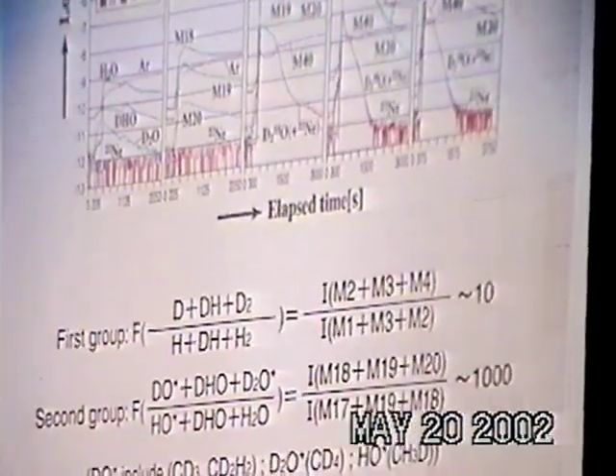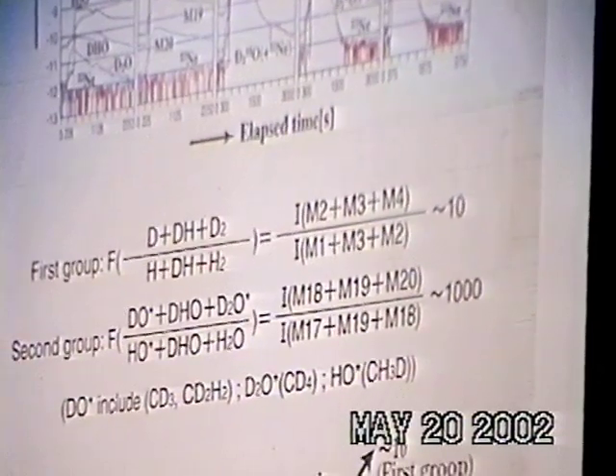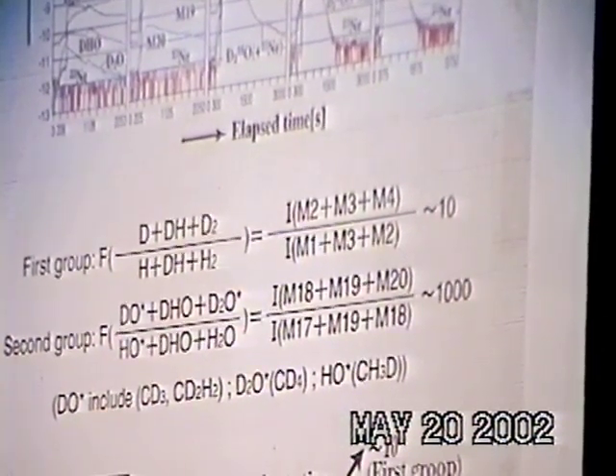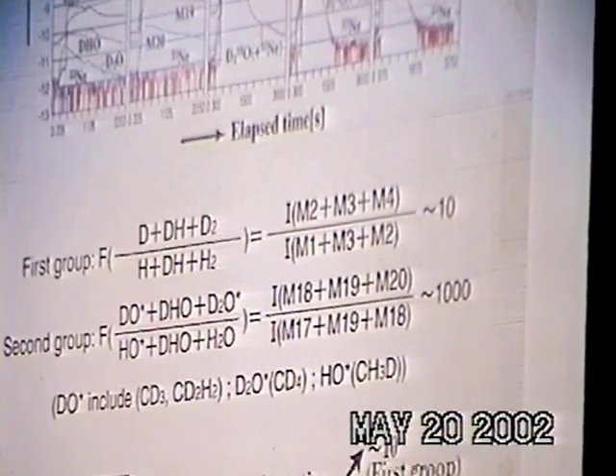By using spectrum intensities in these diagrams, the anomalous intensity difference between D and H atoms implanted into sono powders can be determined by the following equation. Finally, it is concluded that the implantation effect on D atoms is more than 1,000 times larger against H atoms. This is the implantation effect. It is extremely strong compared with H implantation. This event is definitively important to cause solid fusion.